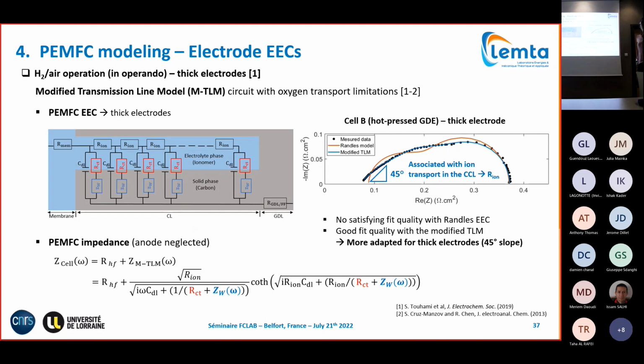Okay, the Randles circuit, again, is associated with thin electrodes. Thin electrodes means it's typically a vertical line at the intercept at the highest frequency with the real axis. But if you have now here a spectrum, see, for thick electrodes, which is characterized by 45 degrees.